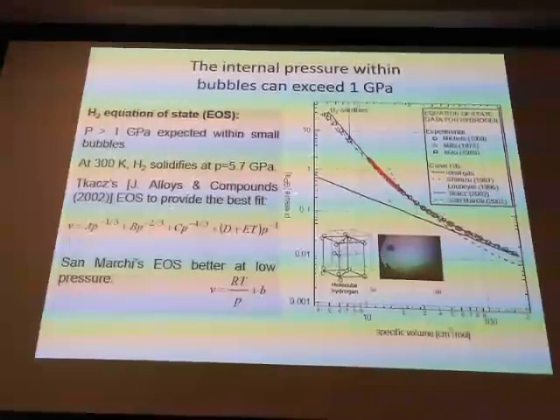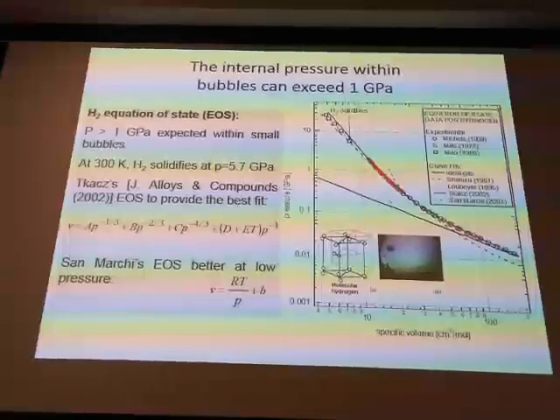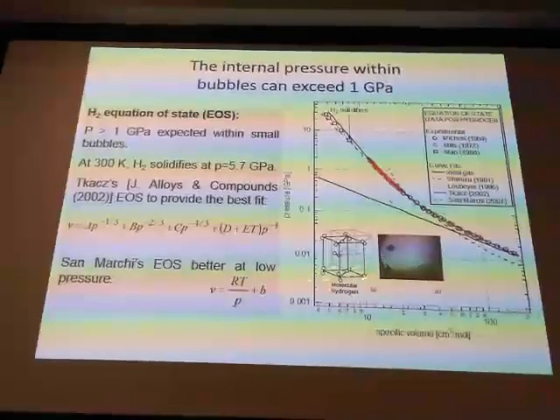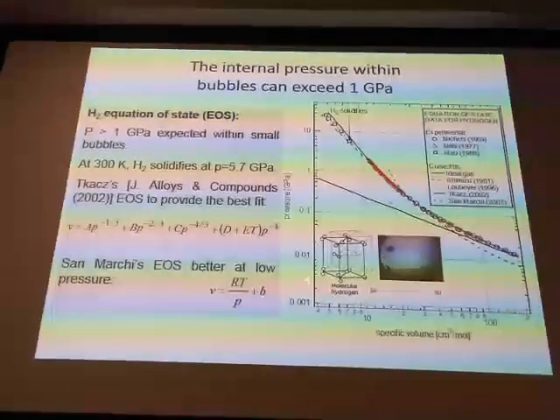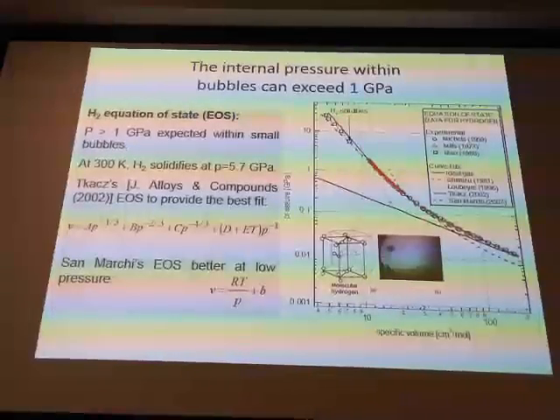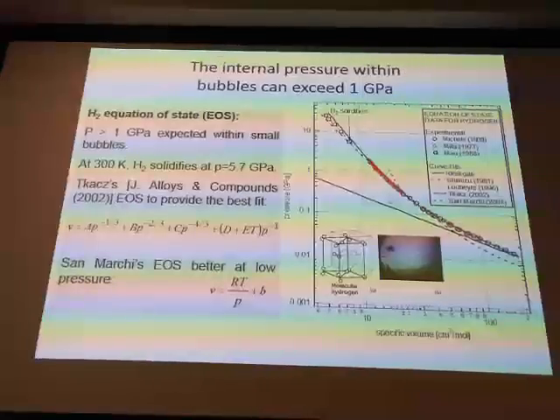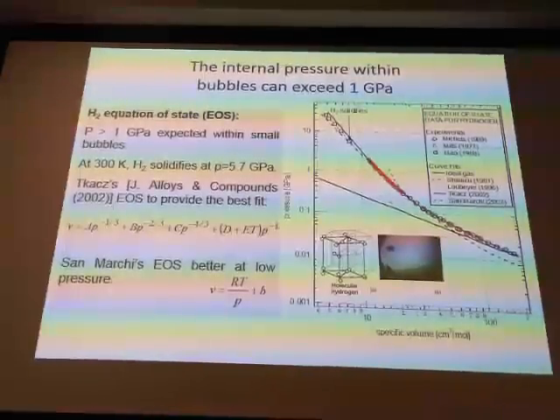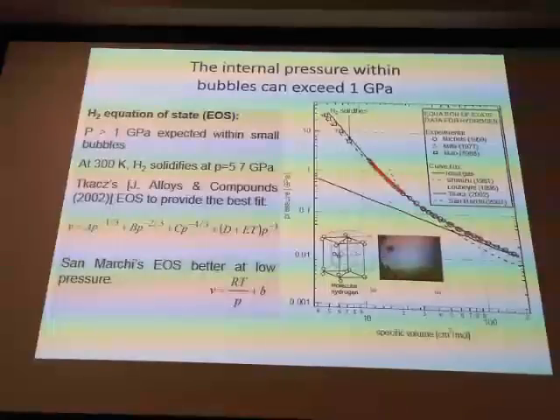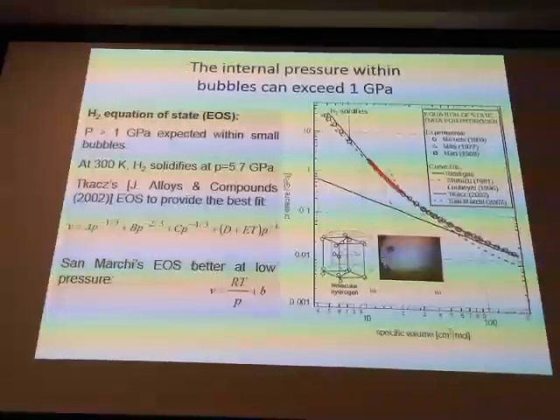And when you think about that, hydrogen solidifies at about 5 gigapascals. And there have been studies at Brookhaven National Labs where they've done diffraction to study the structure of hydrogen, and they found that it actually forms a molecular solid at 5 gigapascals or so. So basically an H2 at every lattice site, and it forms a sort of hexagonal structure. And so you can actually almost approach the conditions that are required for that within these small bubbles. And it's those types of pressures that are required to expand these bubbles by dislocation loop punching, which is thought to be the main mechanism by which they're expanding.